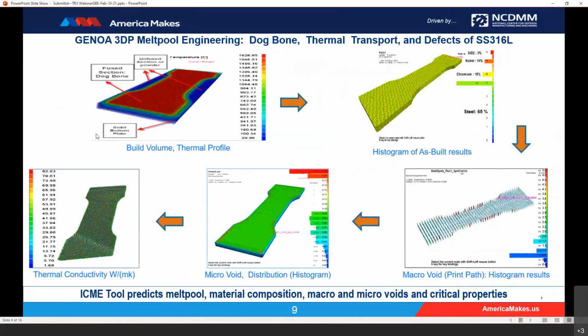Thank you. GENOA 3DP melt pool, addressing a dog bone, thermal transport, and defects in stainless steel. A thermal management analysis is also performed on a macro level scale LPBF printed dog bone sample made of stainless steel. The model size was 25 by 6.3 by 0.8 millimeters and included 1,197,000 elements and 20 layers.